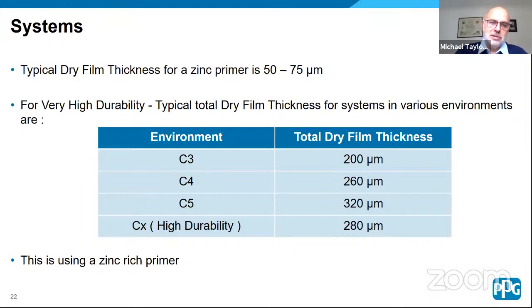And for CX, which doesn't have a very high durability category, CX systems are considered to be highly durable rather than very high durable. So we can't give you a CX very high durable system, but the total dry film thickness there is 280 microns. And this is using a zinc-rich primer. If you use a zinc phosphate primer, then typically you'd be looking at a dry film thickness of an additional 40 to 50 microns for each of these categories.